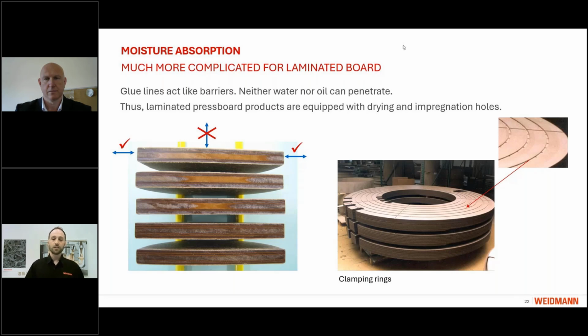For these structures, and due to this assessment, all the big clamping rings, barrier boards, and so on, the real massive structures, are equipped with drying holes and impregnation holes. They are the same and they have the same task: to get moisture out of these channels and oil into these channels to overcome the problem with glue lines.